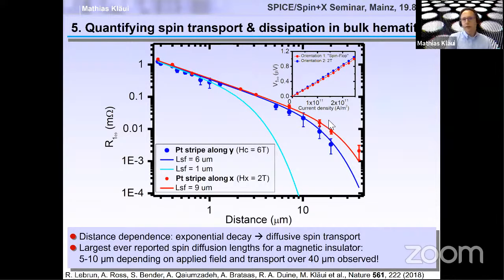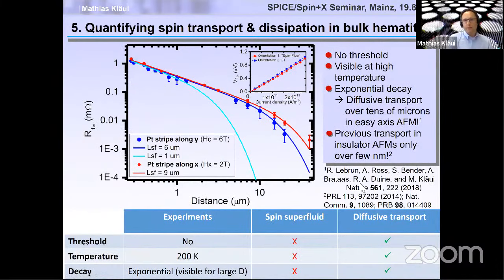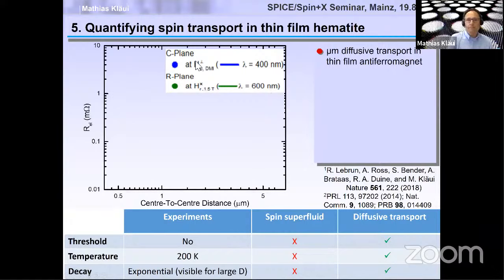Secondly, we found that there is an exponential decay, meaning that the transport in our case is diffusive because we have no threshold current density. It can work at elevated temperatures, and there is this exponential decay. And the key take-home message was that you need to measure for relatively long distances in order to see this exponential decay. Now, what we did more recently is we compared the exponential decay for the same hematite, but for different planes, C-plane or R-plane. And then we found that, interestingly, even though it's the same material, if we look at different planes, the distance over which we can transport spin varies quite a bit. So here over C-plane, we get a distance of about 400 nanometers. For R-plane thin films, we get a distance of about 600 nanometers.